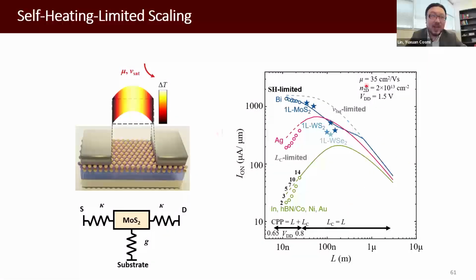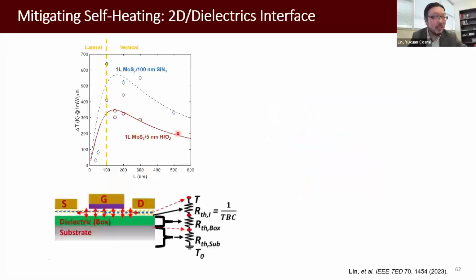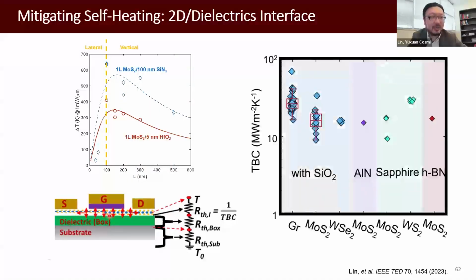Based on that, we can update our projected curve. We can see in the intermediate gate length, about 100 nanometers, the self-heating is the most significant. But when we further reduce the gate length, it may be okay. But if you really want to solve this issue, everything also happens at the interface, especially between the 2D material and the dielectrics. This is from another review article about thermal boundary conductance between 2D material and different substrates. Those are still too low, so the out-of-plane heat dissipation is still not ideal, so we should still work on it.